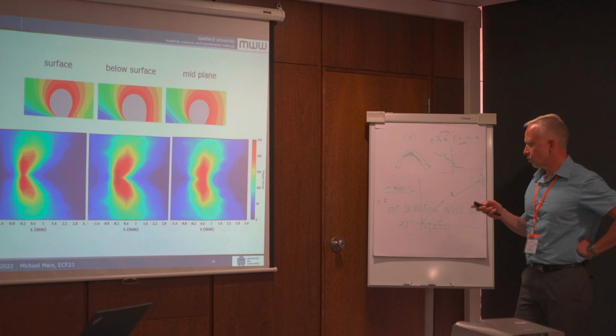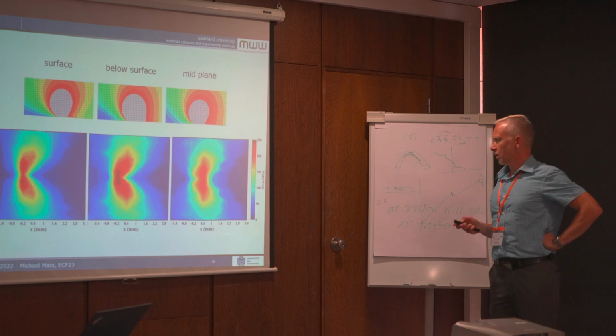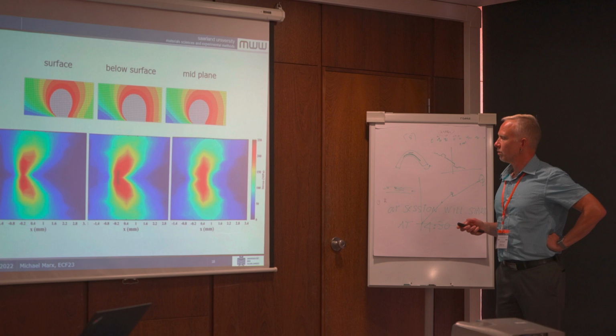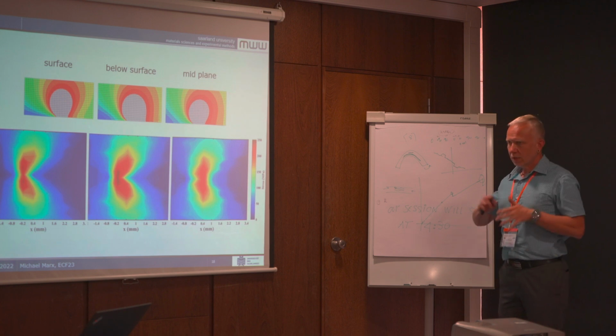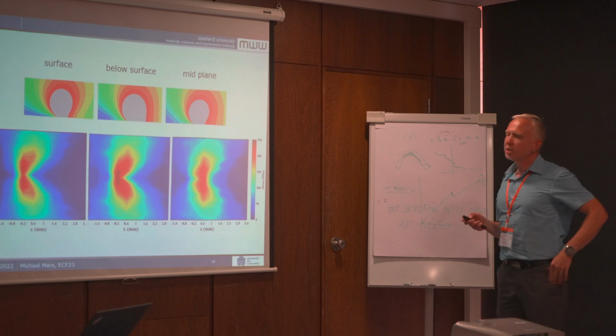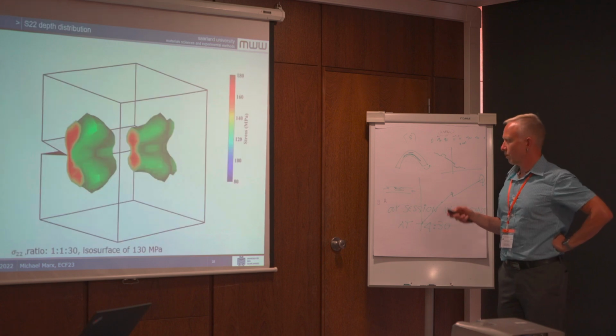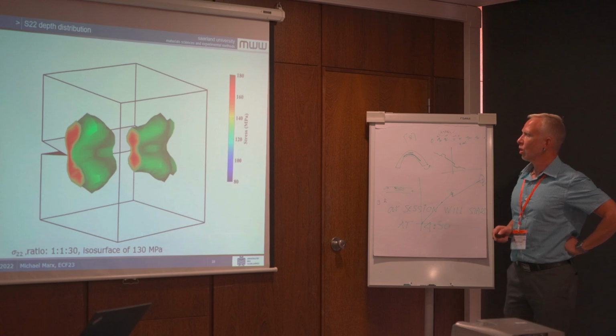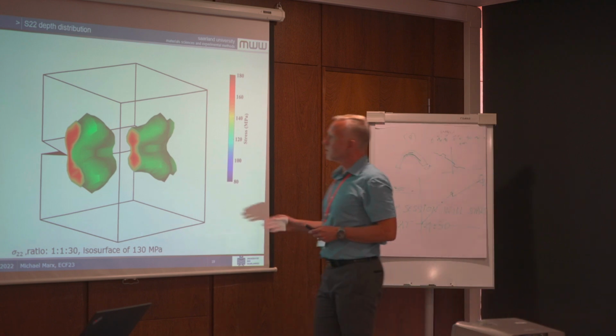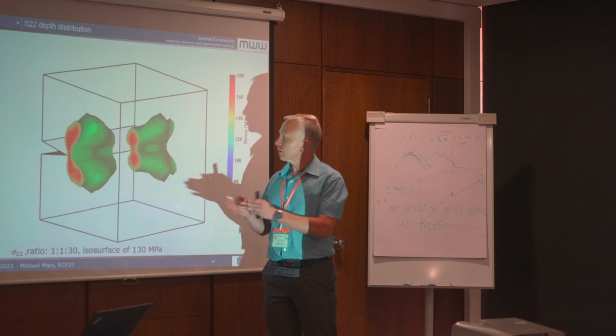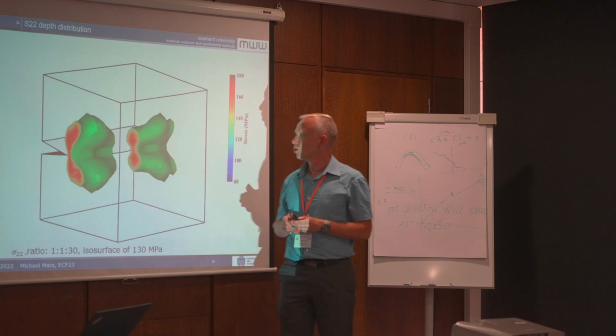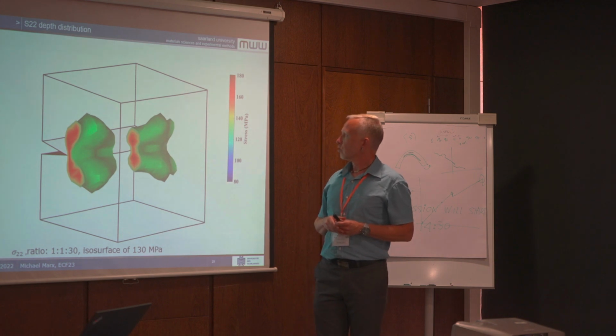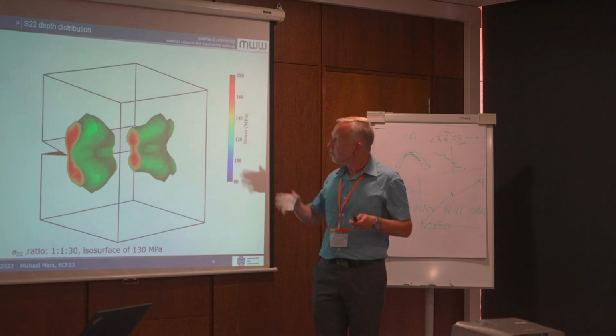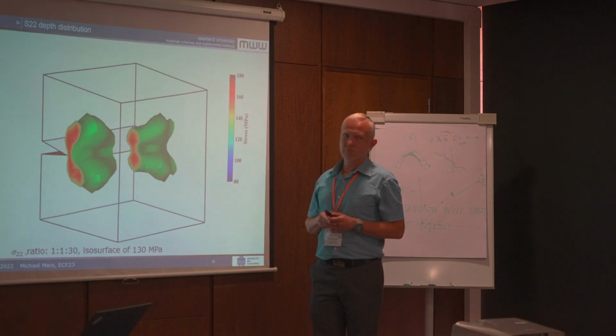Then we have again a reduced size of the plastic zone stress distribution in front of our crack. And then we can also make a 3D image of the plastic zone, and this is how the plastic zone looks in 3 dimensions. So the specimen was too thick to be measured completely, but in the middle part where we have the plane strain condition, nothing should change.